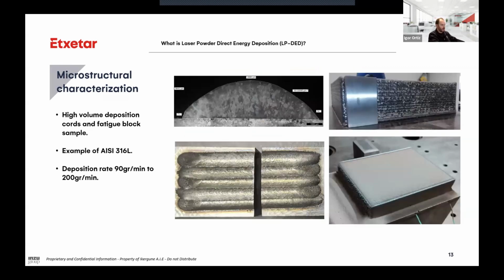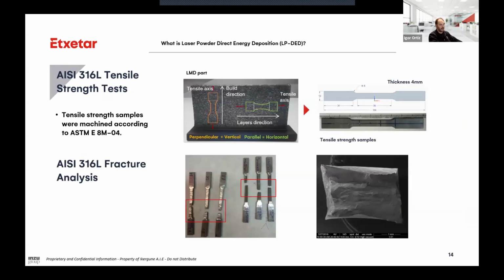So we have done 4 blocks of AISI 316L. On one hand, checking 24 hours non-stop processing with high power laser, that we are capable of manufacturing, and that the system is stable during a 24 hour non-stop process. We have commissioned it and the system works for long times. The optics, the cooling system, the laser source, the nozzles, every item and tool that is involved in the laser powder DED process. And in parallel, we have used these 4 blocks for taking samples for stress strain and also fatigue curves that we are taking in different materials. In this case, AISI 316L.